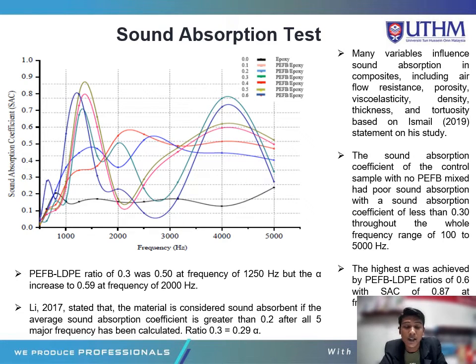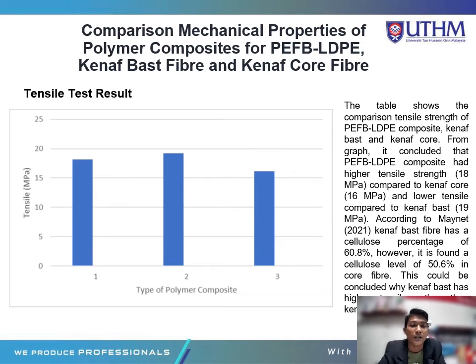2017 stated that the material is considered sound absorbent if the average sound absorption coefficient is greater than 0.2 after all 5 major frequencies have been calculated. Ratio 0.3 after all the 5 major frequencies have been calculated, getting the alpha of 0.29. This is for the comparison of mechanical properties of polymer composite PEFB LDPE with Kenaf bast fiber and Kenaf core fiber.